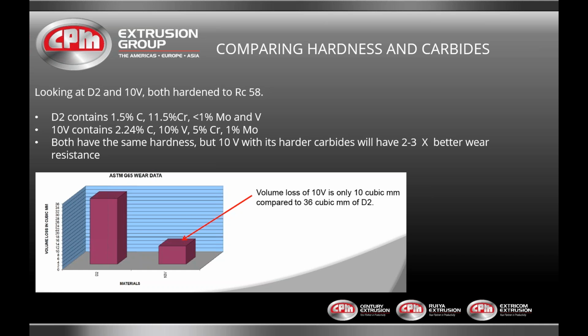10V contains 2.24% carbon, 10% vanadium, 5% chrome, and 1% moly. Both have the same hardness, but 10V with its harder carbides will have 2 to 3 times better wear resistance.